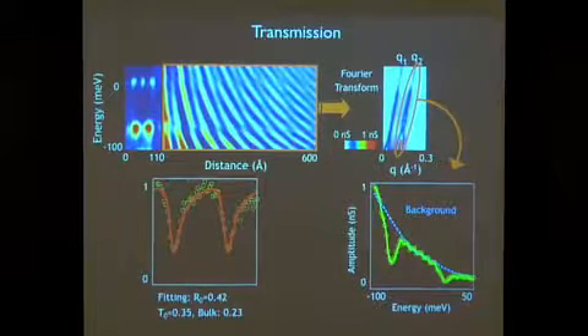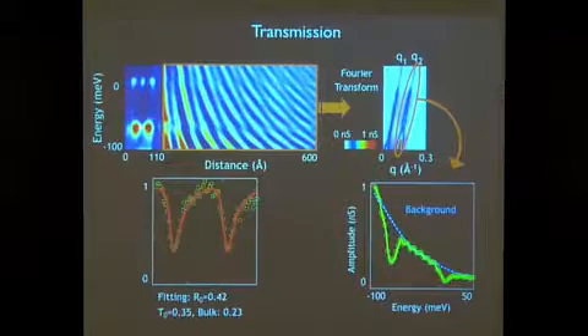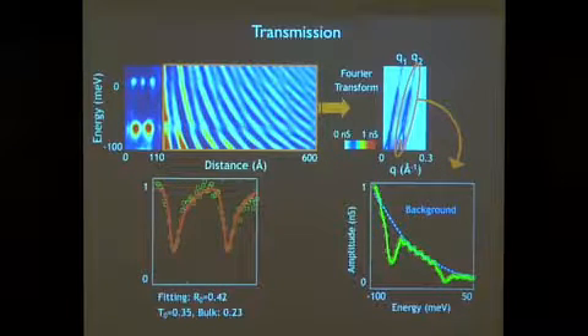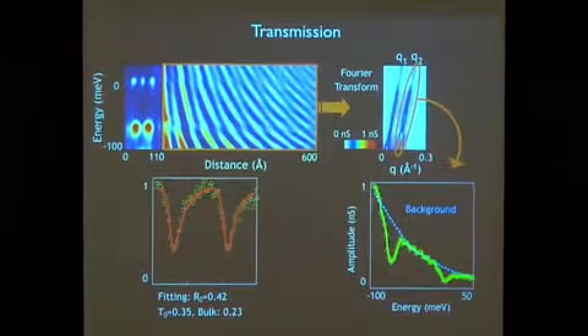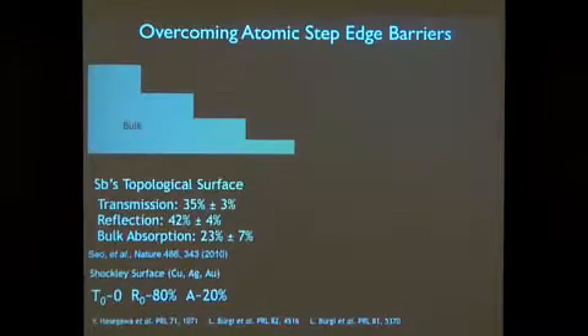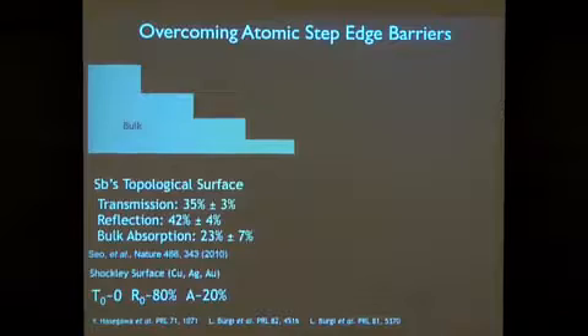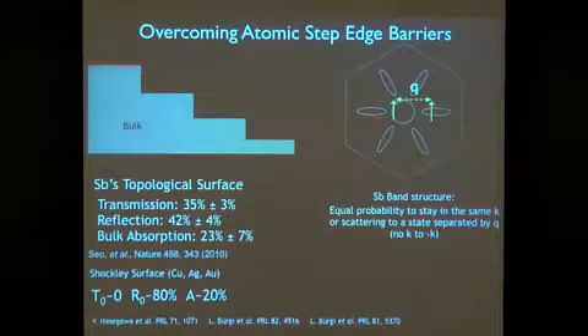from which you can extract the transmission through this very large barrier having to do with this atomic step. And what is surprising here is that we can, of course, get the reflectivity of the electrons looking at the electrons inside the box. What is surprising is that even though you're looking at an atomic step, which is a very large perturbation, electrons are just as likely to reflect into the same spin state or go forward in this material onto the next terrace.